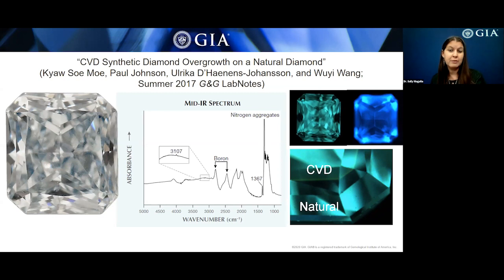The mid-IR spectrum shows peaks for both nitrogen aggregates and boron defects. And DiamondView imaging showed bluish green fluorescence in the face-up view and blue fluorescence in the table down view. The lower right image shows a deep UV fluorescence image that shows the distinct boundary between those CVD and natural layers.